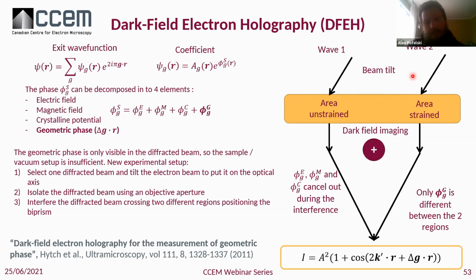Then to see the diffracted beam, you need to select the diffracted beam. So to do that, we tilt the beam. This is to put the diffracted beam on the optical axis. So that's the idea here. This is what we call dark field imaging. Then we isolate the diffracted beam using an objective aperture to have only that. And then we put the biprism underneath to interfere the diffracted beam between them.